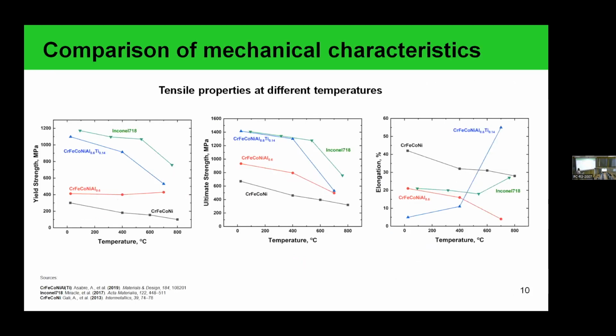In the wide temperature range, we can see how the strength and ductile characteristics of this material evolve with heating to elevated temperature. So for the 4-component system, we see the tendency that we lose the strength characteristics. But if we add aluminum, we can stabilize it at elevated temperature and achieve higher strength characteristics if we add titanium to the composition.